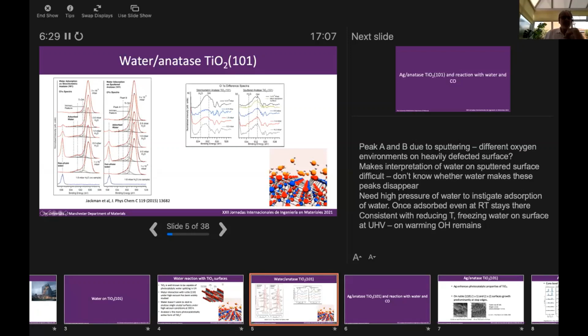When we expose to water, you can just about make out here a small feature appearing at about 533 electron volts, which gets bigger as we increase the water vapor pressure, and this is due to adsorbed molecular water. Okay, this peak here is due to the gas phase water, so this is the water that's just around in the cell that we're using in the system. We confirm this just by removing the sample, and you can still see this peak is present due to the water vapor. When we then pump away the gas, we find that the molecular water disappears. So this is telling us that the molecular water on the surface is quite weakly physisorbed, but the water will react with the oxide surface and generate some hydroxide species at the surface. So we do see some species which remain present on the surface.